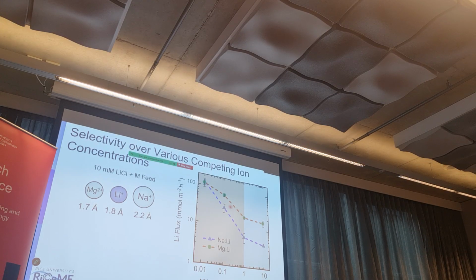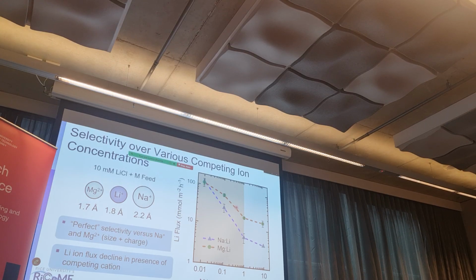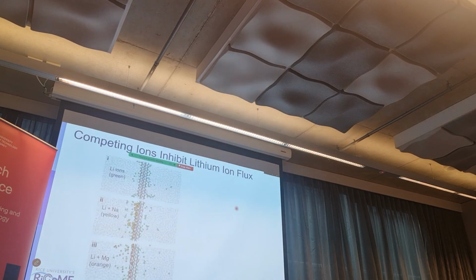The flux decreases significantly with both sodium and magnesium. Still, we get perfect selectivity, the sodium and magnesium do not go through, but they reduce the flux of lithium. So what you see is lithium ion flux declining in the presence of competing cations, and we explain why this happens.